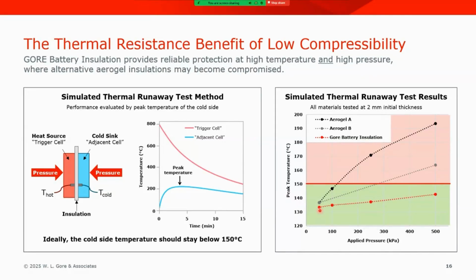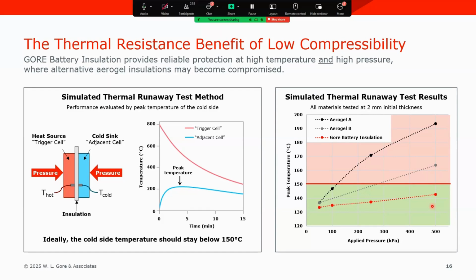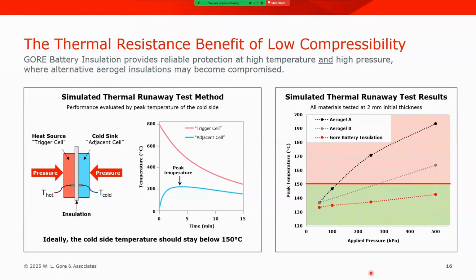GORE battery insulation starts out with an initial very low temperature, again in the same ballpark as the aerogels, but you see even under conditions of increasing stress, it maintains that durable thermal barrier. It's maintaining its R value, its thermal resistance, so that even under 500 kilopascals of stress, we can maintain a peak temperature well below 150 degrees. And this is ideal for the performance of a thermal barrier material. So it's offering a more durable thermal resistance and thermal barrier properties under extreme conditions of high temperature, as well as high compressive stress.